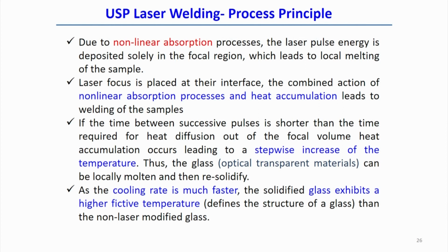So, temperature may not, with the application of the pulse laser, there may not be continuous increment of the temperature. Temperature actually increases stepwise. So, the glass, that means optically transparent material, can be locally melted and resolidified with the application of the ultrashort pulse laser. But at the same time, the cooling rate is also very fast in this case.